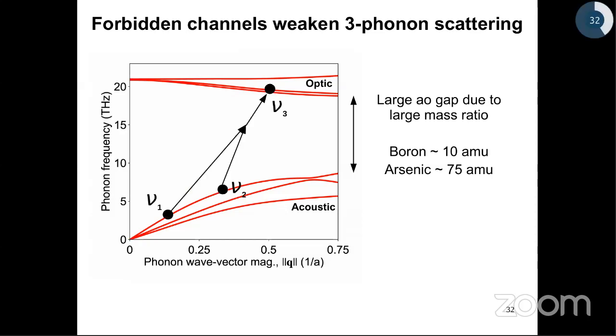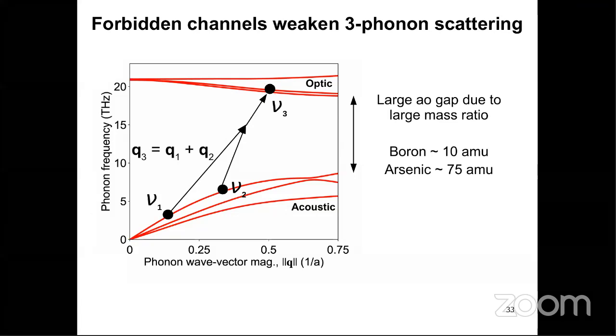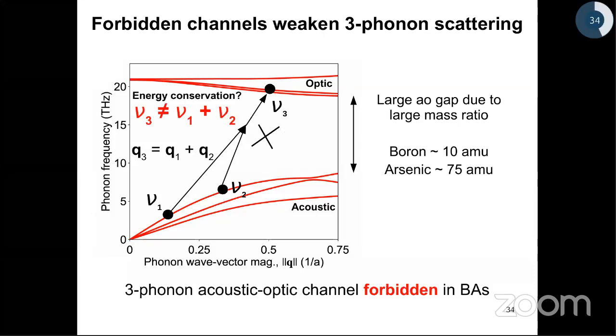Now let's think about a typical 3-phonon scattering process where you have 2 acoustic phonons scattering into an optic phonon. So any scattering process has to satisfy 2 constraints. The first one being the conservation of momentum, or the wave vector. I have chosen these 3 points such that this equation is trivially satisfied. You can see that Q1 plus Q2 roughly adds up to Q3, which is the x-axis. The second constraint is the conservation of energy. So what it says is that the outgoing phonon's energy should be equal to the sum of the